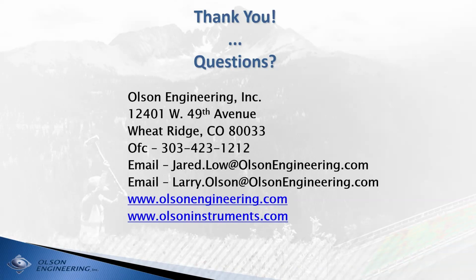Certainly, the question of moisture content comes up. They did sample and get the moisture content for those top soils where they excavated it. We looked at it a little differently in terms of corrosion evaluation. This is the existing conditions, and at those depths it's kind of the ambient moisture content. Whatever it is, that's the resistivity. We don't think it was saturated by any means. But even so, seeing that it was below the criteria of 3,000 ohm centimeters or 30 ohm meters is the problem that exists in the backfill soils as placed. So I don't think their quality was quite as high as they thought when they placed them originally. Hopefully that helps you in that regard.